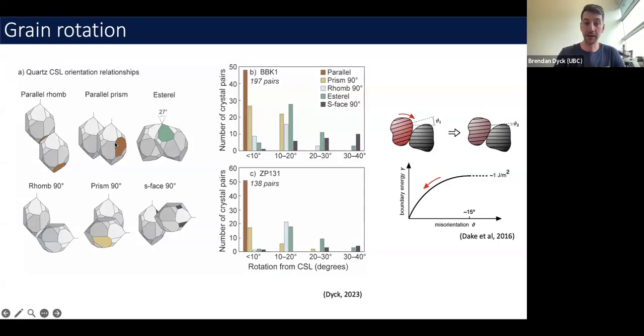So what we're looking at here, again, are these different orientation relationships. To spell out this acronym in full, it's quartz coincident site lattice orientation relationships. It's another way of saying the low energy orientation relationships. And if we look statistically at the number of crystal pairs that are within 10 degrees of one of these orientation relationships, we can see, both with parallel, the 90 degrees, and the Estérel twins, those are highest as we move down from 20 down to 10 degrees. And then the frequency of that drops off as we get to higher energy.